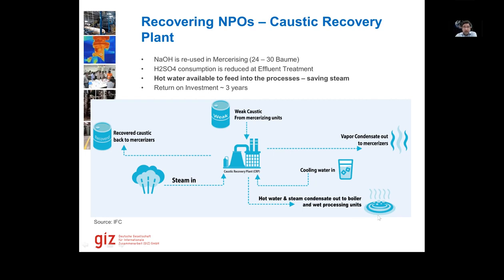And so they are able to recover sodium hydroxide at 24 to 30 Baumé, which is quite high strength. H2SO4 consumption is also reduced at the ETP, where they had to neutralize this alkaline solution. And hot water is available to be fed to the processes, saving a lot of steam as well. Calculating all these savings, the return on investment is less than 3 years in this case.